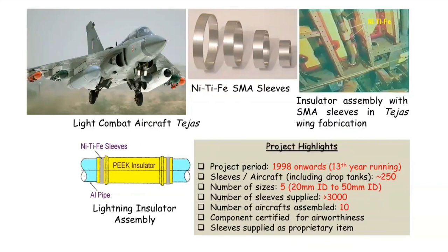Now, there's another feature which I think if Dr. Ashok later on wants, he can also say whether I'm right or wrong. But this aircraft is made slightly flexible, and that is one of the features of this. And there are some dividends aerodynamically when you make the structure slightly flexible, which also means that all these pipings which are not on the neutral plane will be pulled apart. So the total stresses that this material sees has to be held by this particular nickel titanium. It has to hold out against all that. So you need a constant stress. It is not just interference stress in terms of minor interference. It needs to be a constant stress that applies. And that is what this simple application gives.